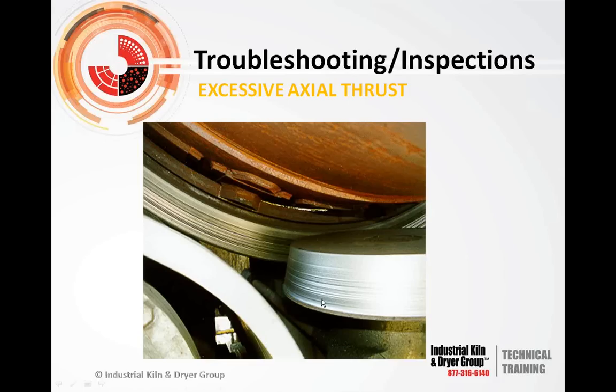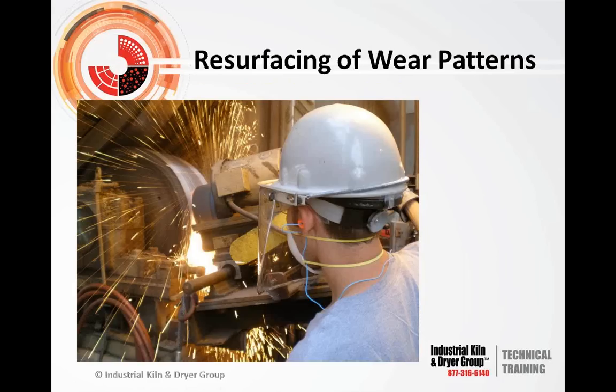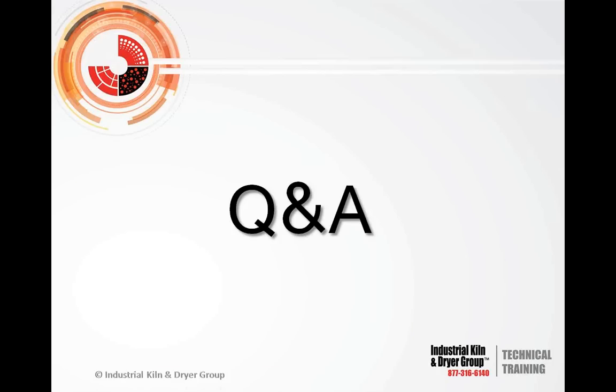What will happen is as you lose that material, the unit is actually moving in the direction that you're losing the material, and you can lose contact between your gear and pinion and cause premature failures on that. If you get these types of wear patterns, about the only thing you can do is grind them out. And that's one of the things that you want to avoid. Anytime you have to grind, you're going to be taking material and life of the component off. So basically, you want to try to control what's going on with the unit while you're operating.